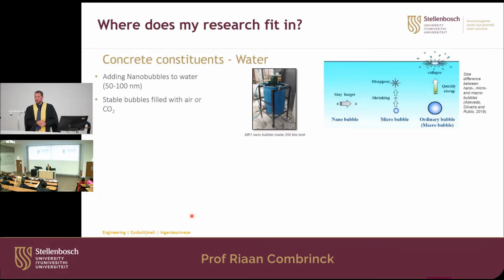So in terms of water, what have I done? We've been adding very small bubbles, nanobubbles, to water. These bubbles are about 50 to 100 nanometers. A strand of hair is about 50 micrometers, so this is about 1,000 times smaller than a strand of hair. These bubbles can be filled with air or CO2, and it's a stable bubble. In other words, it doesn't disappear. It stays there. It doesn't collapse or disappear with time.